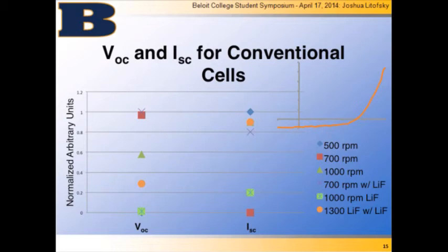So next, we wanted to look at the fill factor and the efficiency. The max power that we get out, P equals IV, so power equals current times voltage, is when the current multiplied by the voltage is the greatest. The fill factor is taking the current that the max power is at and multiplying it by the voltage that it's at and dividing it by the open circuit voltage times the short circuit current. This gives us a way to quantify the internal efficiency that the cell is working at, so how well it is performing in relation to how well it can perform.